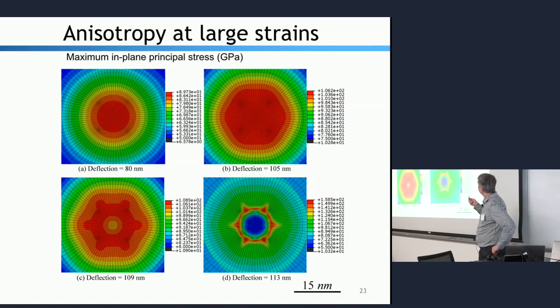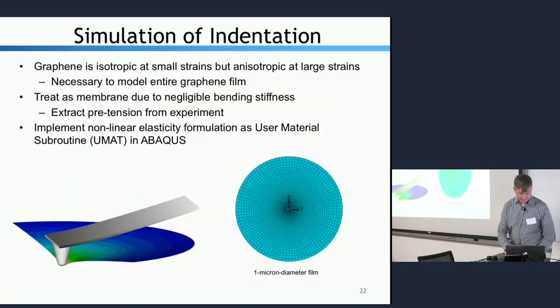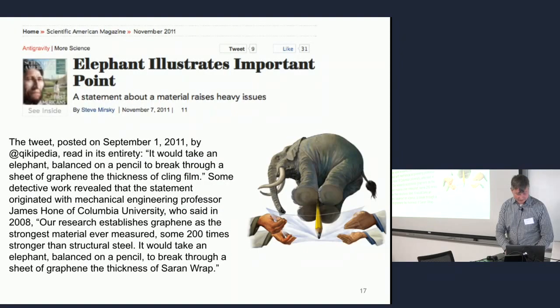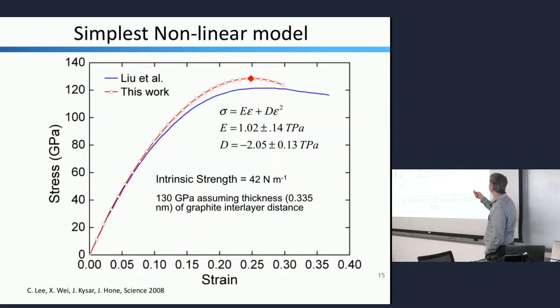As you start to go to higher deflection, you start to see other terms turn on, and those other terms are not isotropic. So the higher order terms see the crystal symmetry, and you can see that becoming more and more clear as you go on. The other interesting thing you see is that this is right before fracture. You actually notice something interesting. You notice that the stress has actually gone down, right? And what that is, I can point it out here, right? It's kind of the same thing here. So you can actually take part of your material over the edge and go over the top of this stress strain curve. Right?